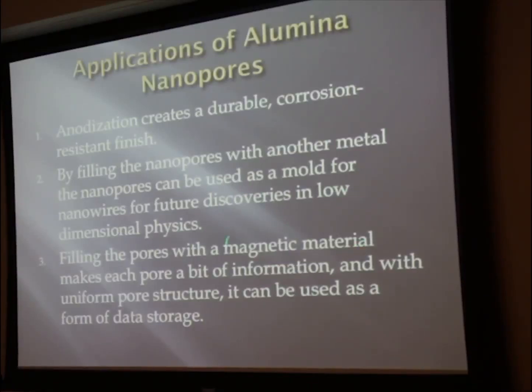As for actual applications, one of them is that we can fill these tiny nanopores with a metal, and by filling those, we make little nanowires. Those are very important because with standard classical wires, you have things like Ohm's law, V equals IR, all the normal physics you learn in electromagnetism. But those tend to change when you go to the nanoscale. There's different physics governing how things behave for such small diameters, and to actually test those models that have been formed, you need to have these nanowires, and this is one of the ways to construct them.